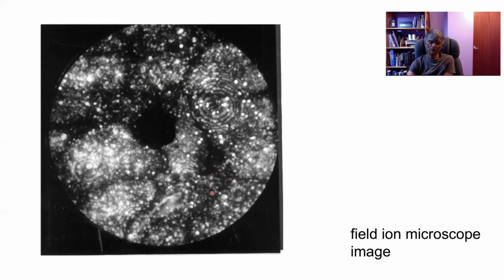and if you squint your eyes, you can see these dark features, and those are dislocation cell boundaries with intense dislocation density, and the coherent regions are reduced dramatically in size. So we've got to 5.5 gigapascals, which is 5.5 billion pascals, or newtons per square meter. Really astonishing strength.